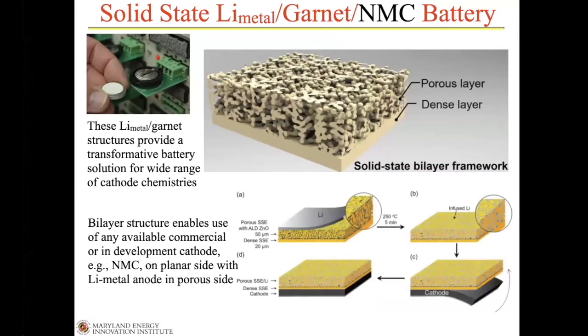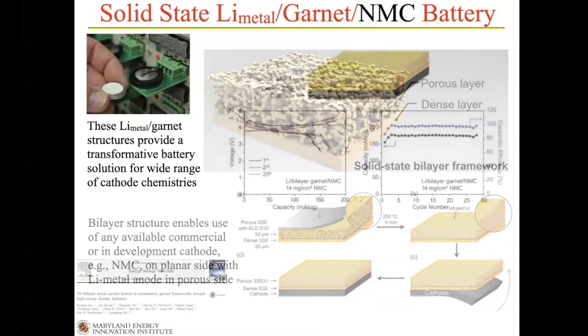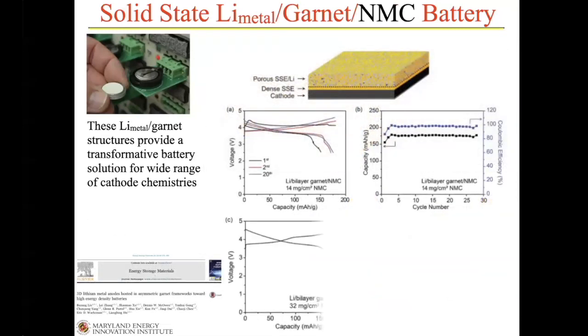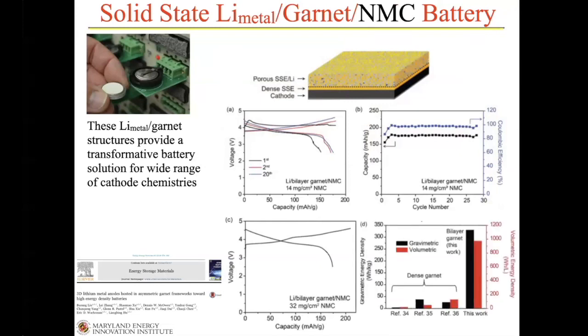So we're also now making bilayer structures, which are a dense porous layer. And the advantage of this versus the trilayer is this allows us to use commercial cathode materials like NMC. And here's some initial results showing that. And in fact, we're able to achieve on the order of well over 300 watt hours per kilogram on a gravimetric basis and about 1,000 watt hours per liter using a conventional NMC cathode on one side with the lithium metal and the dense supported garnet layer on the other side.